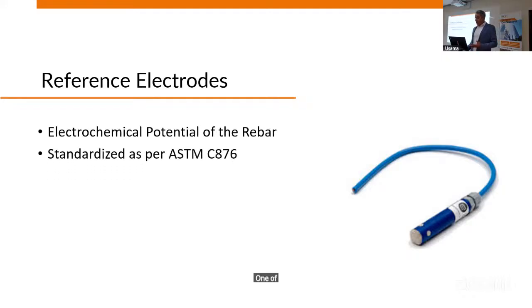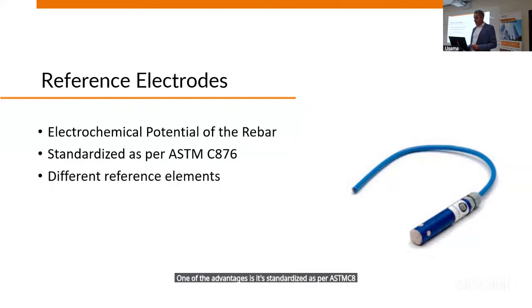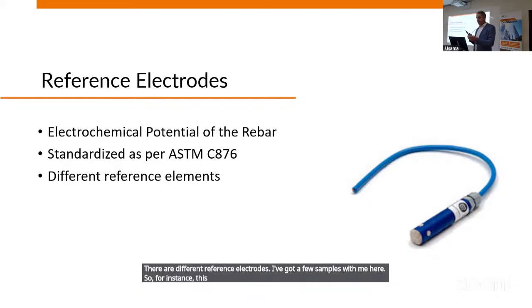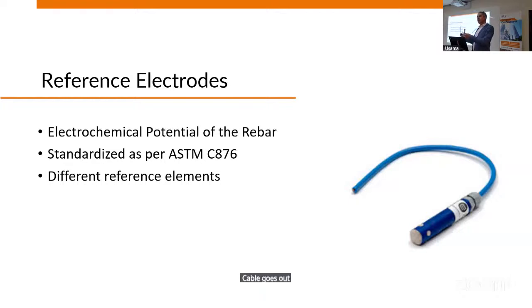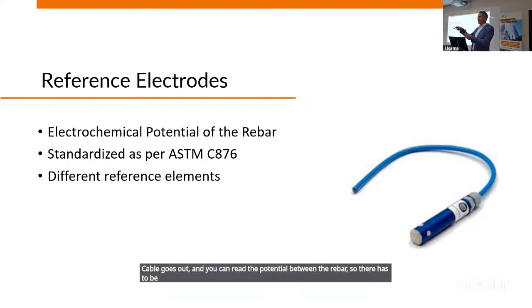One of the advantages is it's standardized as per ASTM C876. There are different reference electrodes. I've got a few samples with me here. So for instance, this is a manganese oxide reference electrode. It's a solid reference electrode that can be embedded in concrete. Cable goes out and you can read the potential between the rebar. So there has to be a lead to the rebar and another one to the reference electrode, and you can monitor the potential over time.